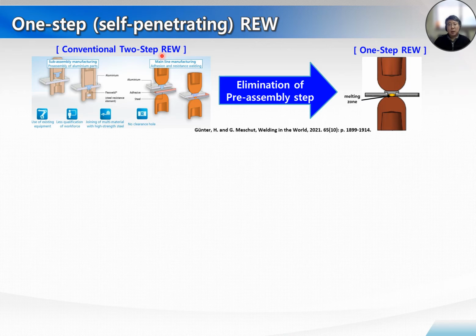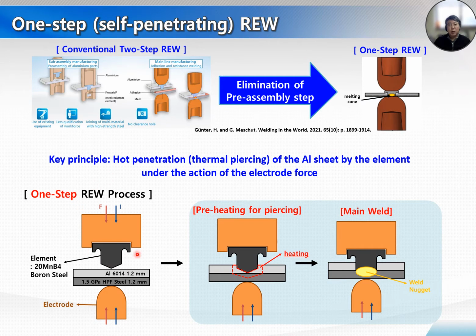Therefore, one-step REW, resistance element welding, was proposed that omits the pre-assembly step and starts from the mainline manufacturing by punching or piercing the element into the upper aluminum and simultaneously performing resistance welding with the lower steel in one step. In the case of this one-step resistance element welding, the preheating process of the aluminum sheet piercing using a special jig device and the main welding process are carried out continuously.